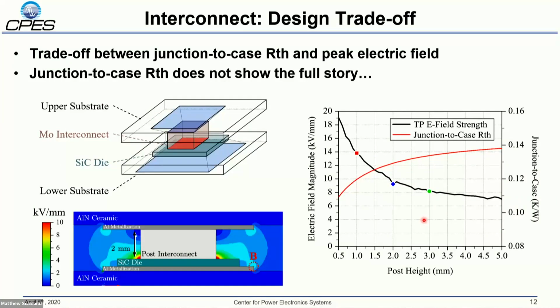So in terms of this post interconnect, there are some interesting trade-offs that emerge when we talk specifically about the height of this interconnect. Part of it is an insulation problem. Because this is a vertical silicon carbide device, we end up with a potential difference between the top and the bottom substrate. And so as we reduce the height of this post, those 2 substrates move closer together and result in electric field crowding on the edges of the substrate. So from an insulation standpoint, we're motivated to make that post as long as possible. Of course, that's counter to what we would desire from a thermal performance standpoint, where we want to minimize the height of the post to improve heat sharing between the top and bottom substrate.